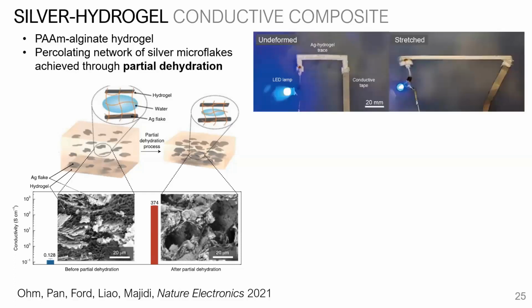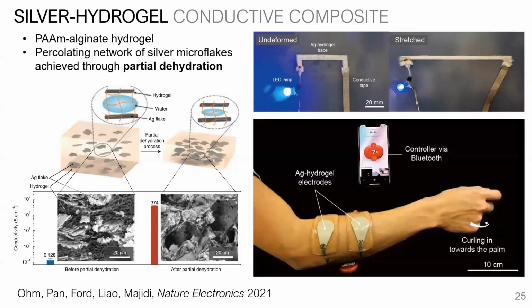And so for that, we just took the naive approach of filling it up with a high volume fraction of these silver flakes. And then we took advantage of the fact that over time the water will evaporate. As that happens, you start removing some of the water between these silver flakes. You can actually form a somewhat connected percolating network of silver flakes. And in this partially dehydrated state, you can get a hydrogel that has fairly high electrical conductivity, hundreds of Siemens per centimeter. So well within the range of what you need for digital electronics.